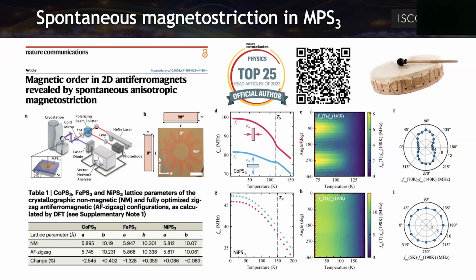If we perform a fully ab initio calculation, in this case, with no external parameter, we observe that effect. We observe a compression of the a-axis and expansion of the b-axis for the cobalt. This is also happening for the iron, and nothing is happening for the nickel. This is almost very constant. We were testing also different magnetic orders, and then the effects go in different directions. So it's very related with the magnetism. Magnetism is driving all these interactions.